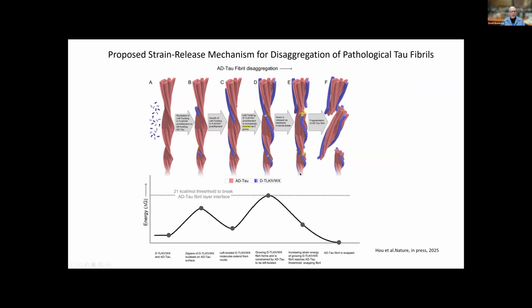So here's what we think is going on in cartoon form. Here's the peptide or small molecule added to the pathogenic fiber. It's nucleated on the surface. The concentration is high, so it binds to the tau fiber and forms a nucleus. Because it's ordered, the entropy goes down, so the free energy goes up. But once it's nucleated, now other molecules or small molecules add easily to the fiber, and they bind, so the energy goes down. But as it continues to grow, now the fiber is metastable, so it exerts a strain partly because in this case it's the wrong-handedness, but also for some other reasons.